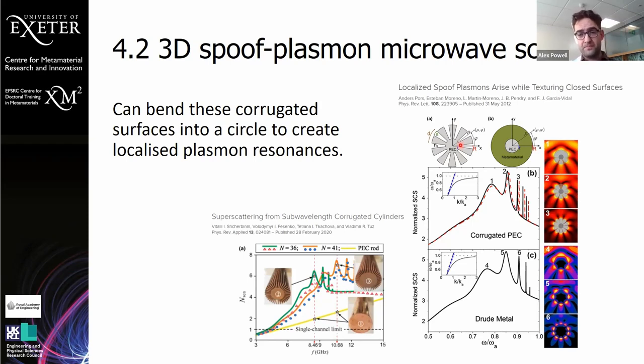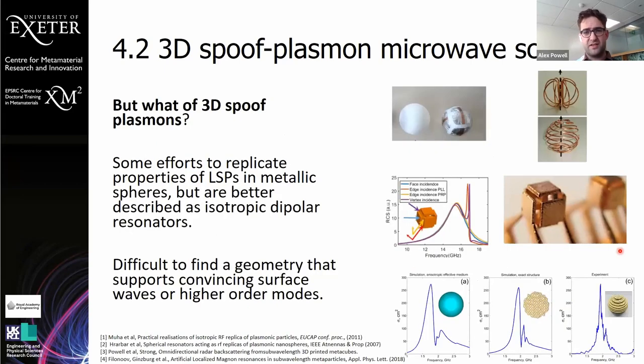And they found that this corrugated structure was actually able to act as an effective medium with an effective permittivity, and the scattering cross-section you got between this corrugated material and this effective material that you could model based on the properties of it are pretty comparable, especially at the low mode orders. Not perfectly comparable. And there's recently been interest in making more 3D samples of these as well. But this is not fully 3D. This is 2D or extended 2D.